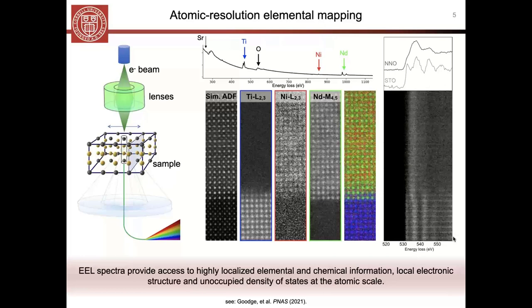You can see as you go from the substrate at the bottom of this profile up to the top, into this thin film in this case, there's a dramatic change in the shape of the oxygen K edge. That really allows us to extract the detailed chemical information that we're really interested in. The power of EELS is really being able to marry this kind of chemical analysis with this kind of spatial resolution.